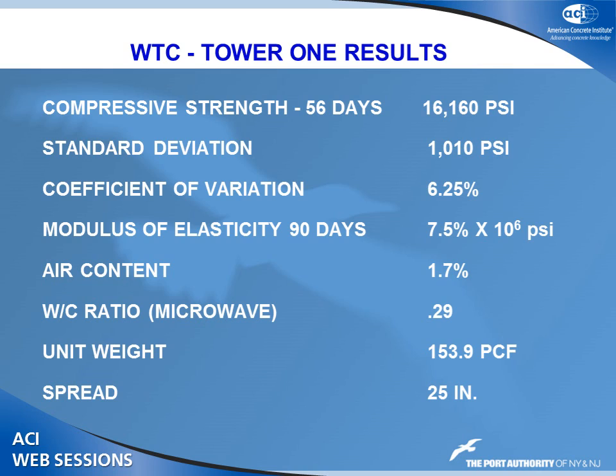The consequence on the Port Authority job is that we have an end result specification. And here's what we want: we want 95% of the concrete to be above 14,000. If you dip below 95%, we reserve paying you the full amount. We reduce payments on the price of the concrete, not in place, by 50%. We also give a bonus of 6%.